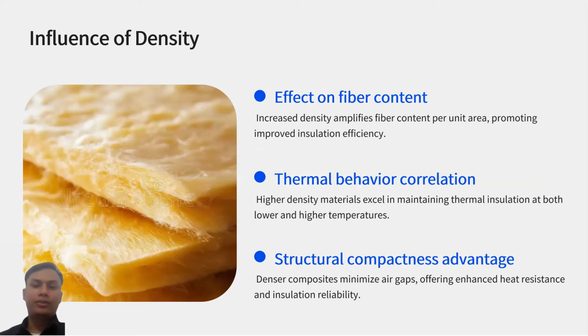Influence of density. Effect on fiber content. Increased density amplifies fiber content per unit area, promoting improved insulation efficiency. Thermal behavior correlation. Higher density material excels in maintaining thermal insulation at both lower and higher temperatures. Structural compactness advantage. Denser composites minimize air gaps, offering enhanced heat resistance and insulation reliability.